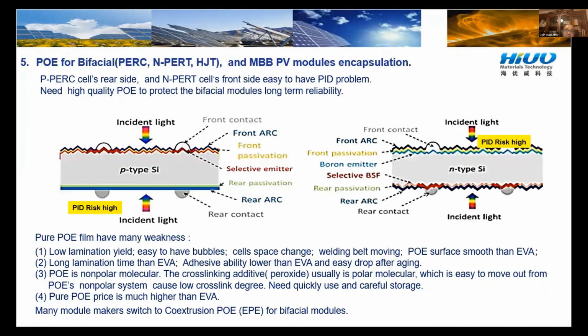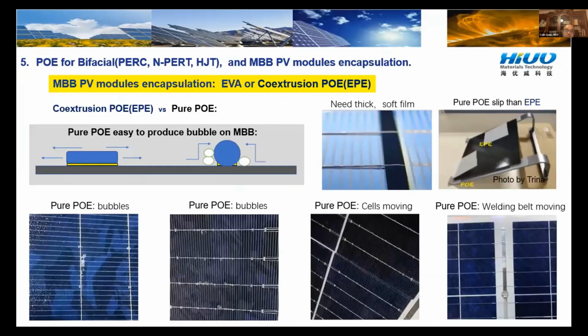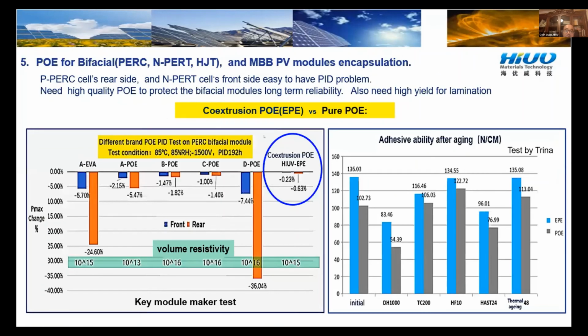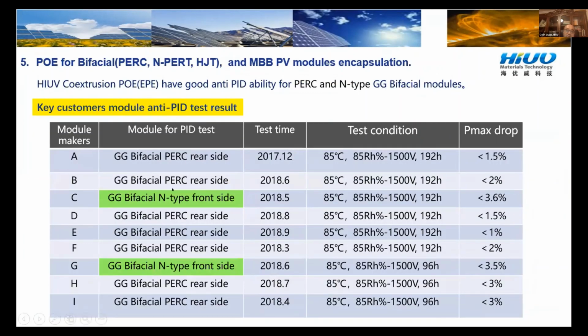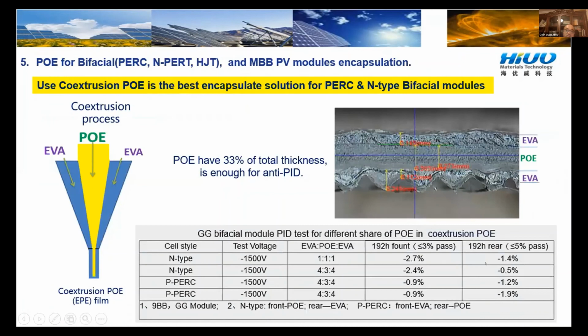Okay. So next, I will describe polyolefin with the EPE structure, which can be much better than pure EVA for lamination yield. Its anti-PID ability also shows better than some pure polyolefin. A lot of module makers have tested our material during the last 2 or 3 years, and all gave really good feedback. With our co-extrusion structure like this, even with less than 30% polyolefin inside, it can pass their very strict PID test.